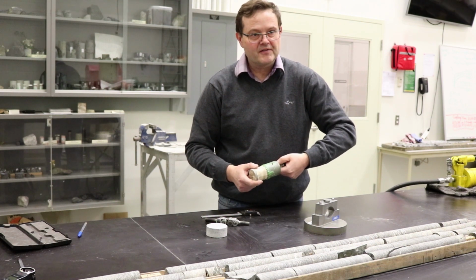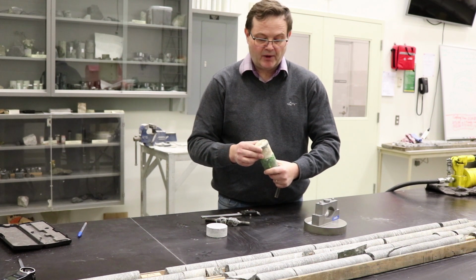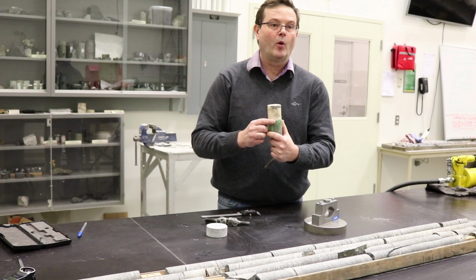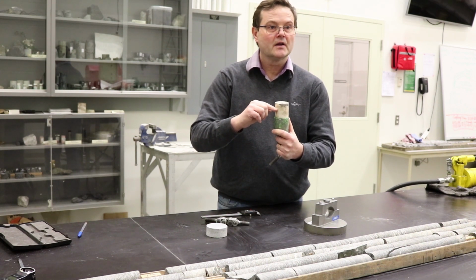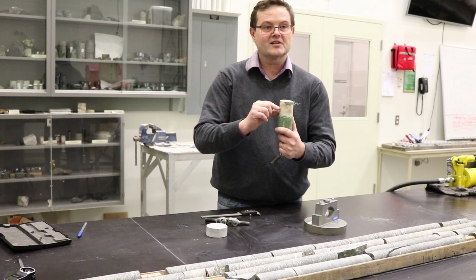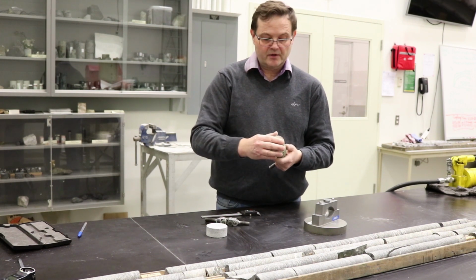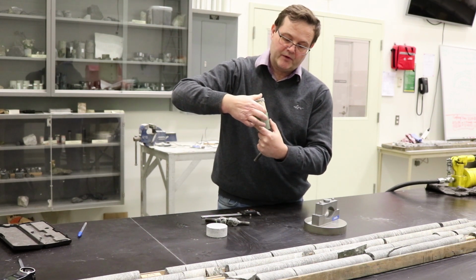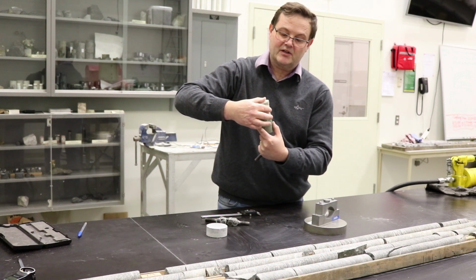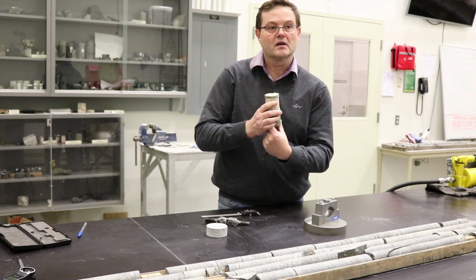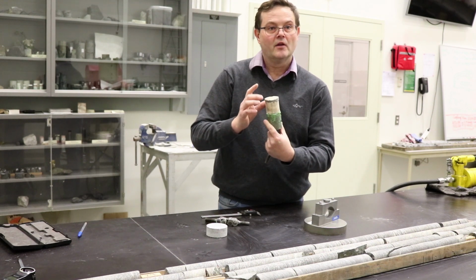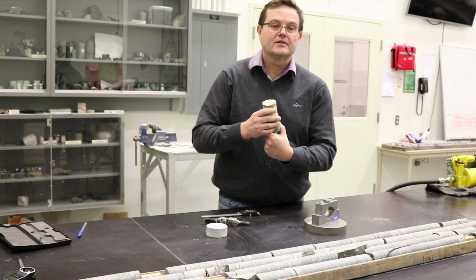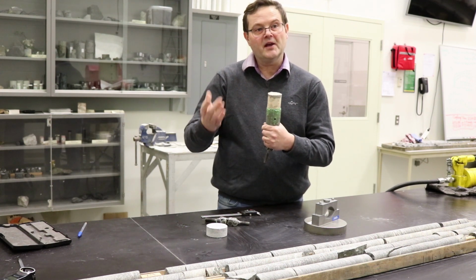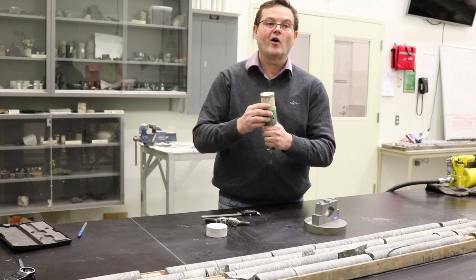However, many times what's going to happen is instead of the sample breaking somewhere in the middle, so we can record the tensile strength of the sample, the sample is going to break at the glue joint between the steel platens and the rock sample, and we're essentially recording the strength of the glue joint, not just the strength of the sample. So many times we have to repeat this experiment, and it usually takes a long time for the glue to achieve full strength, so it's not going to break on the glue joint.